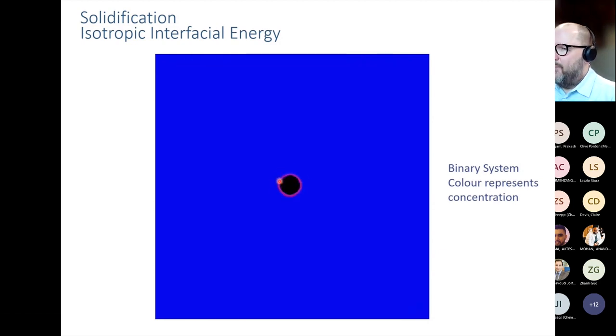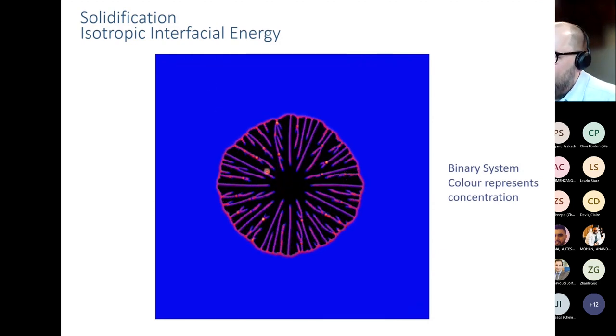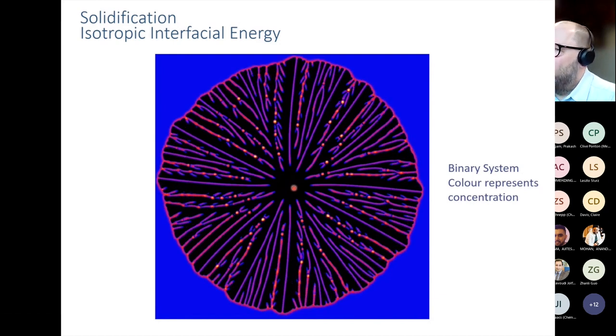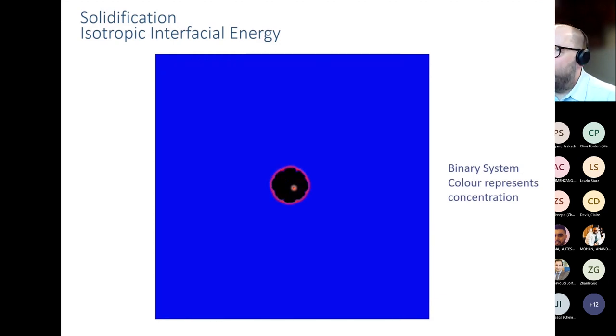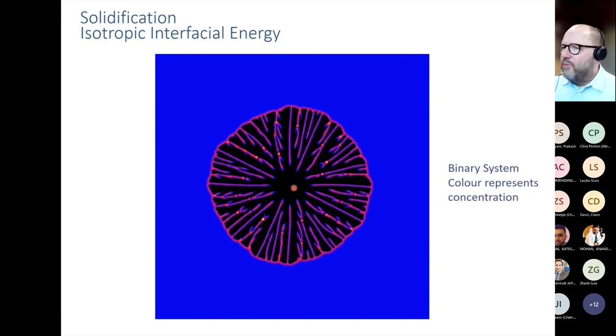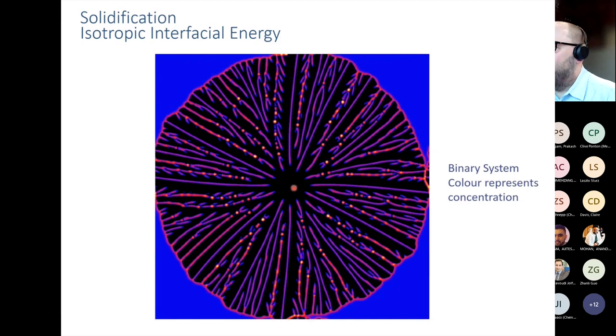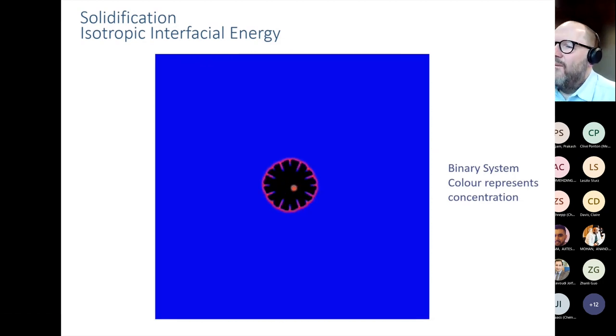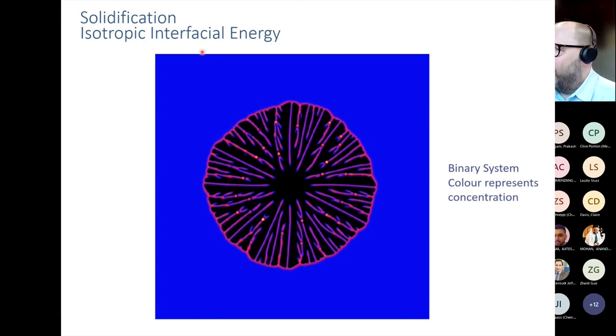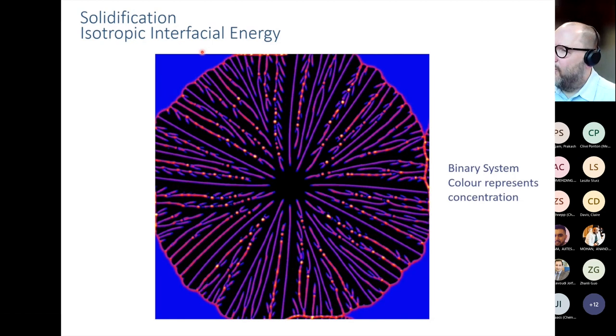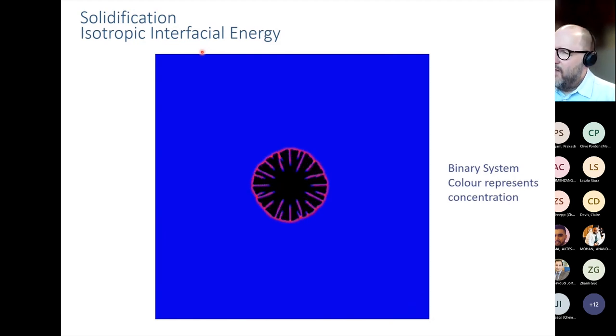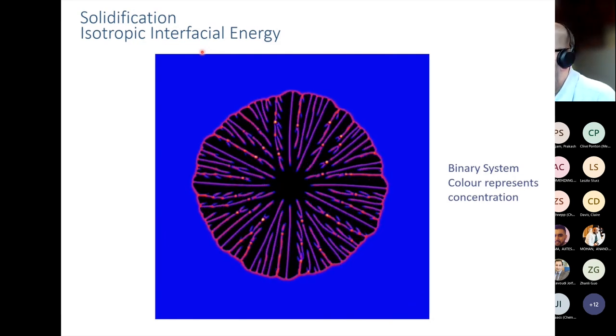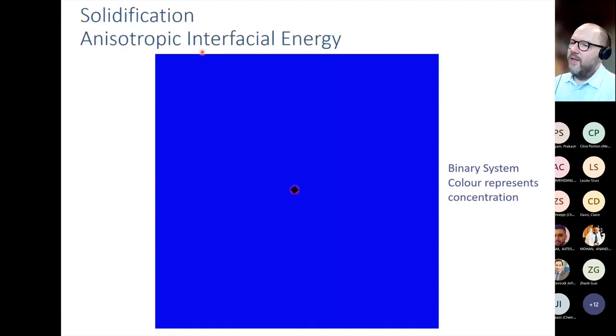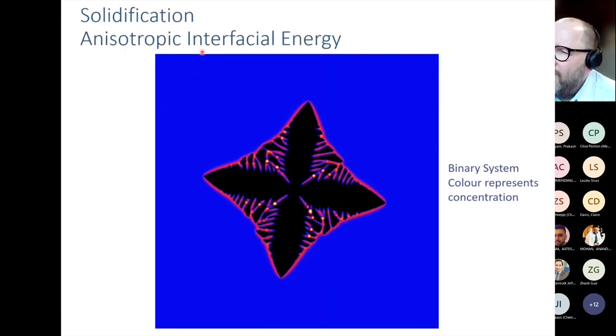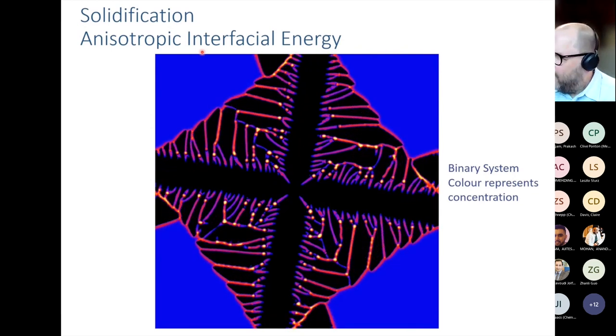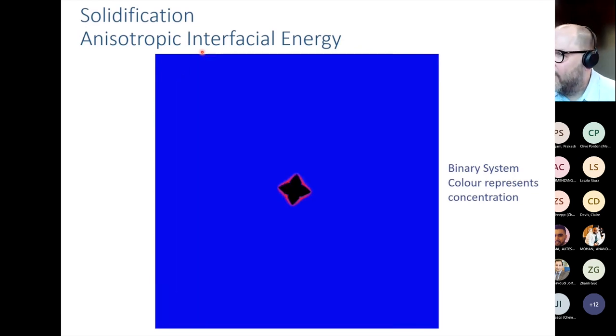We find the interface breaks up and forms these deep channels with enriched liquid, and we form what's typically called a seaweed structure. We also see that there's no preferred growth direction. This grows almost like a sphere, except for the perturbations at the interface formed by the channels. This is the case where the interfacial energy has been treated as isotropic. So there's no preferred orientation of the interfacial energy, meaning the interfacial energy doesn't have any minima for specific crystallographic directions. If we introduce just a few percent of variation in the interfacial energy and leave everything else exactly the same as in the previous simulation, we get exactly this.